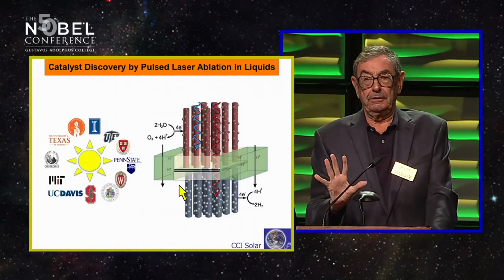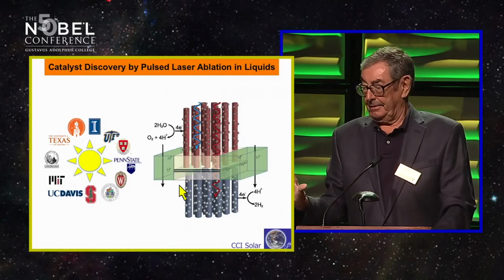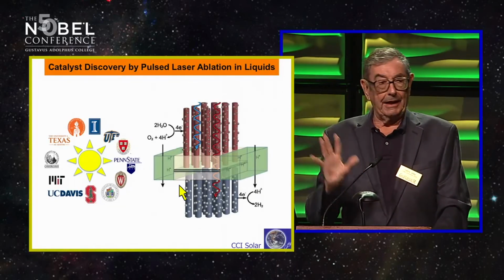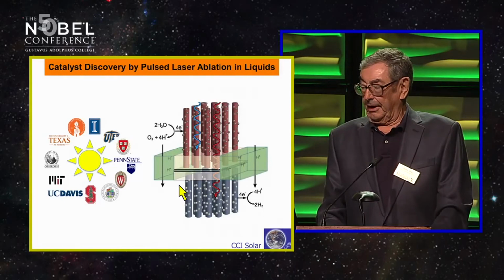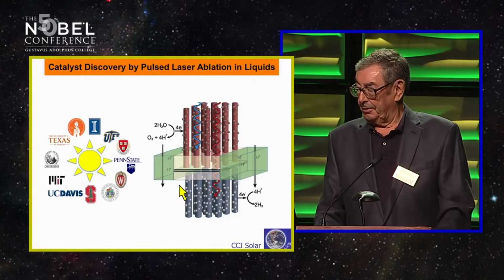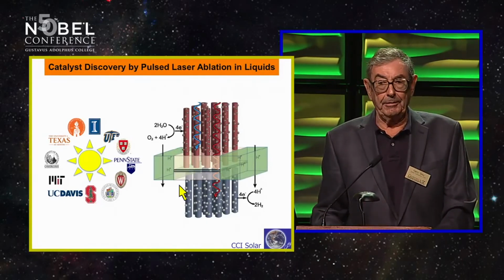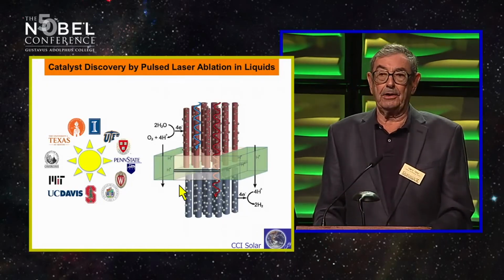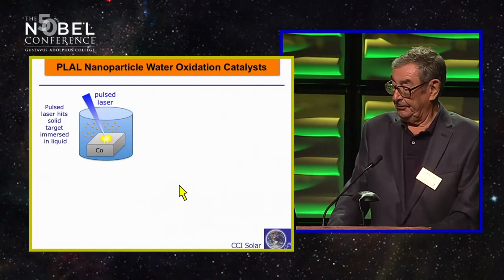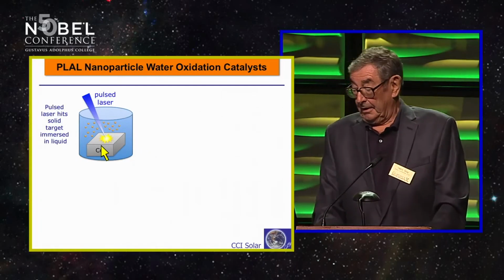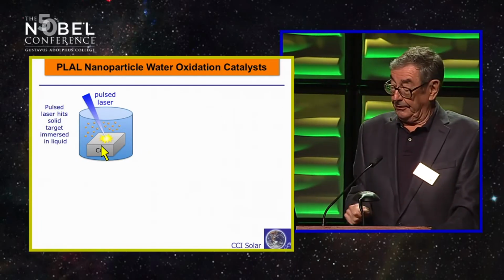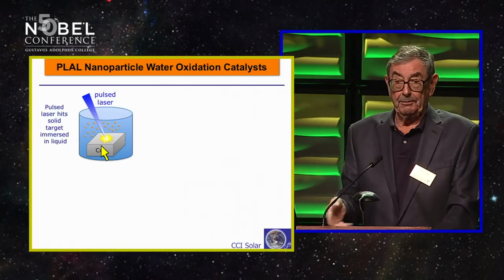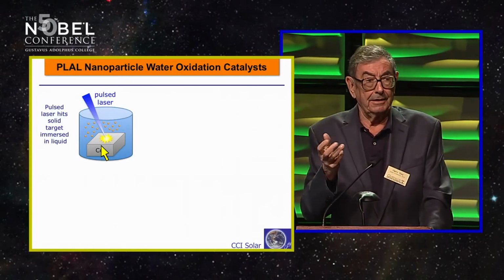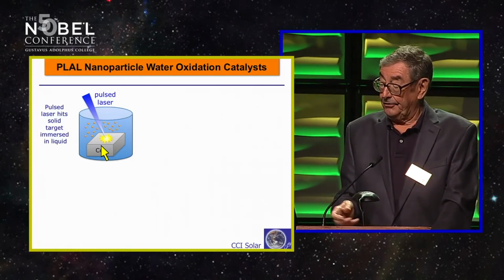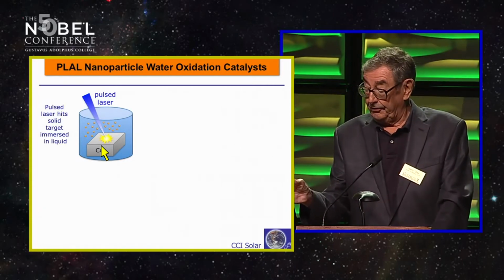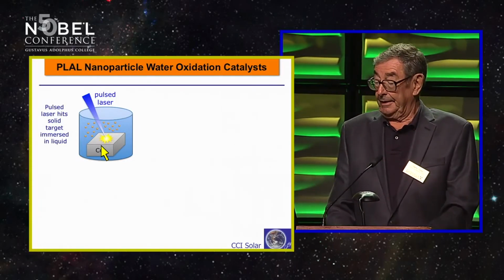So what we do is we take the ideas and we have a very nice way, we got lots of big lasers. So we have a method called pulse laser ablation in liquids that we formulate these materials into nanoparticle catalysts. And here's the way it works. We train a high-powered laser onto a metal target with one metal that's the main metal that we want to put in the catalyst. And we put the other metals in an aqueous solution around it, and we hit this